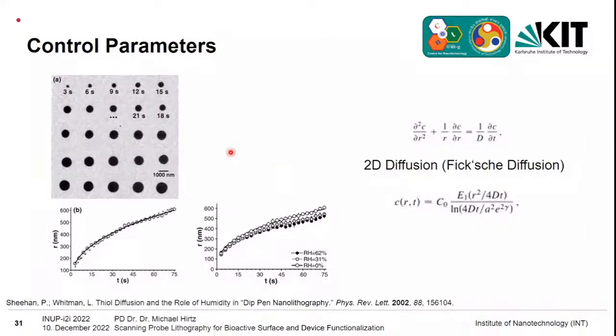This also gives you two obvious control parameters. One is the contact time. So the longer the tip is in contact with the surface, the more material will transfer. And the other thing is the relative humidity. So if you have a high humidity, then usually for hydrophilic materials, more material can go from the tip to the substrate because the water meniscus is bigger. This is, in the case of thiols, theoretically well understood because you can model it with a 2D diffusion model, a regular Fickian diffusion. This means that you can think of the AFM tip as a kind of point source, and the molecules come down to the surface and give you a 2D diffusion. So this is why they grow in this circular fashion with time.